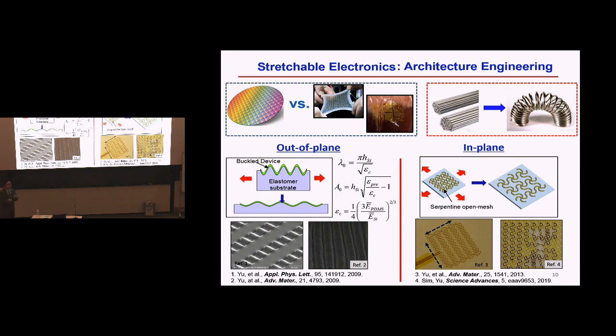Macroscopically you stretch this, it's very soft. But once we have the electronics, which we have been really thinking about moving forward, that electronics and the organs or tissues or cells interfacing with the electronics, especially the cells, have a feature size in the range of a few to tens of microns. So now the challenge is that the cells are so soft, but they are also so small and cannot see the macroscopic mechanical softness. They only see the local mechanical property of these structures, which are fairly rigid, in the range of 100 gigapascal. So basically, there's a mismatch between this intrinsic material property and the tissue or the organs or cells we have been interested in.